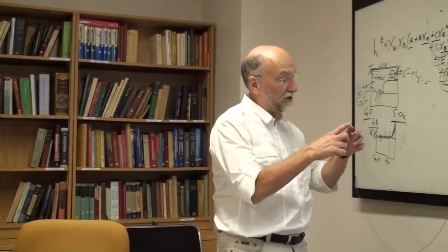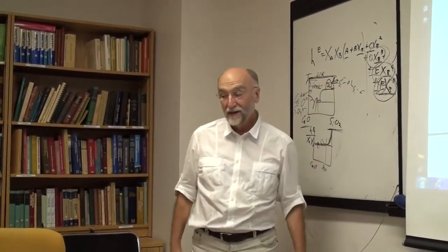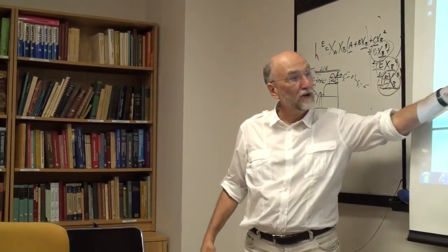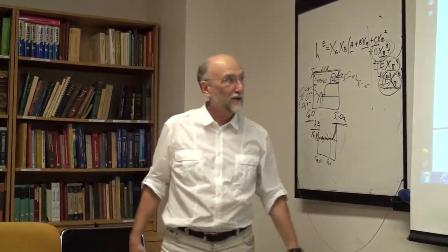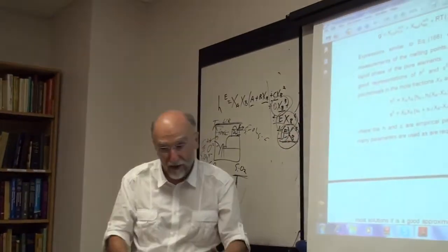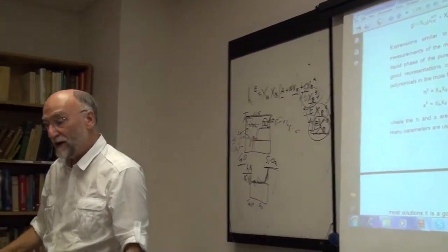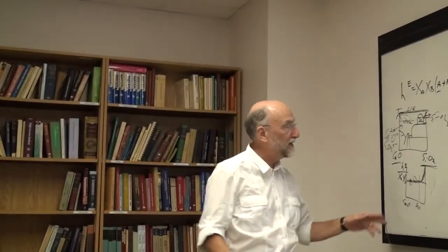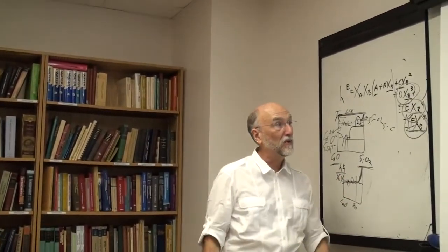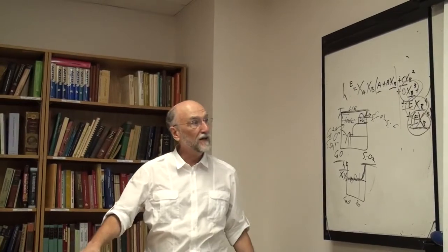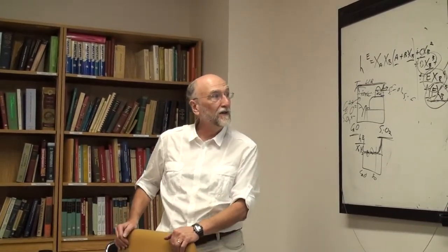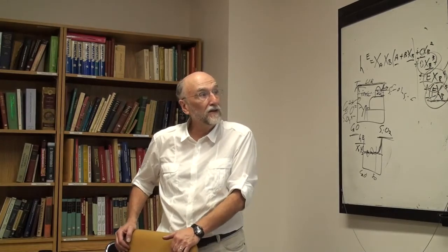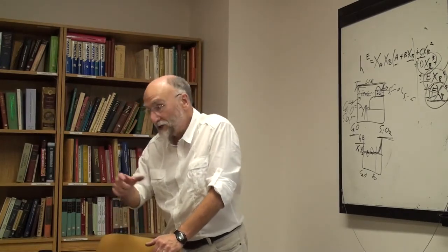And even if you manage to fit your three binaries around a ternary system, you manage to force fit your binary systems to a polynomial, and you get reasonable looking fits in your three binary systems. Okay, doing this, you're going into the ternary system from the binary, making an approximation, and when you're approximating a ternary system from a binary system, you are necessarily making a physical approximation. You're not just making a mathematical approximation. And if your physical assumptions are wrong, then probably your prediction will be wrong.